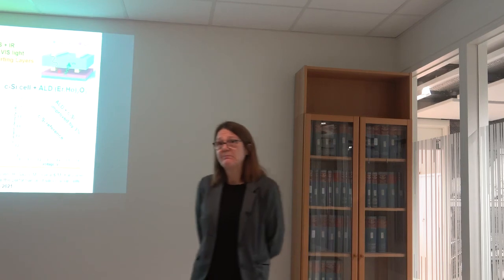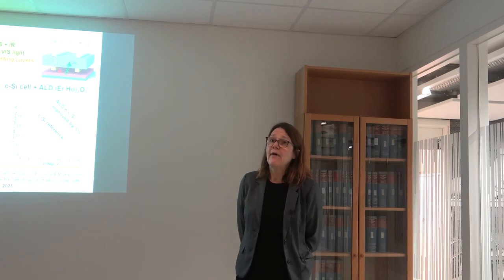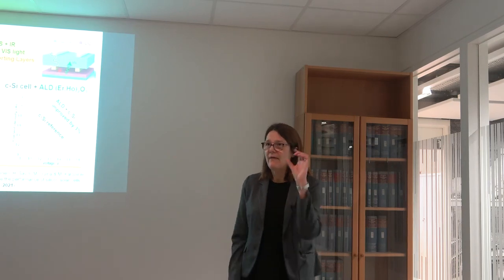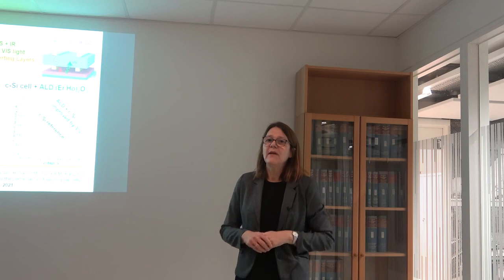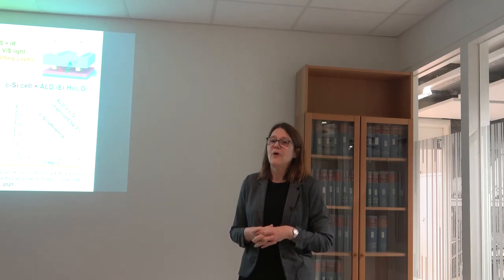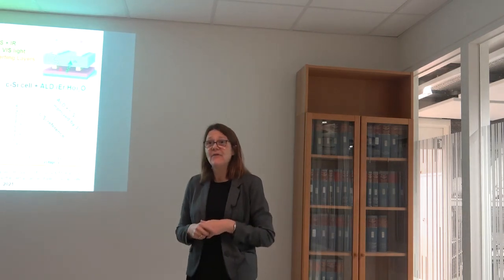The volume fraction of the effect is the same for all different gradient configurations? Yeah, we fixed the total film thickness and the number of organic layers for those. And we have done quite a lot of statistics for this very specific system. I think we have altogether 100 different compositions. We have used very simple statistical analysis to look at the factors, like the thickness of individual layers and the degree of gradient. We showed by this simple analysis with the 100 different compositions that our conclusions were seen from this kind of simple statistical analysis.